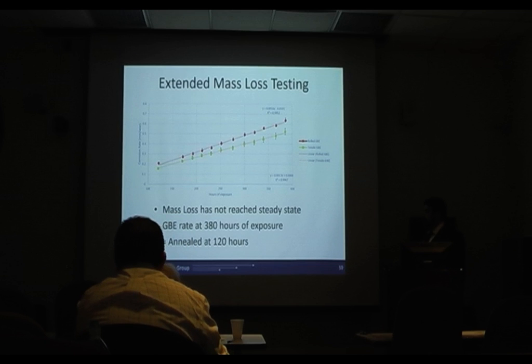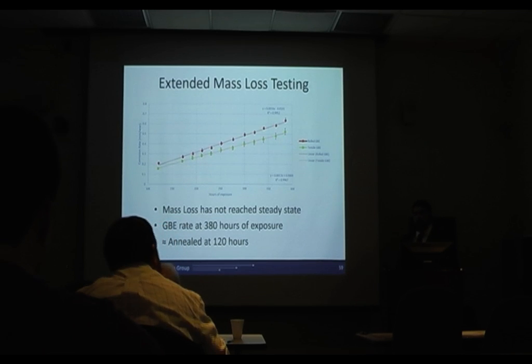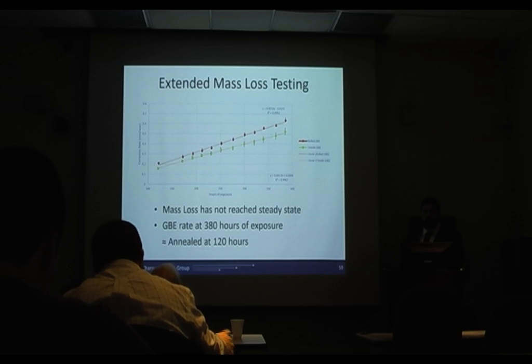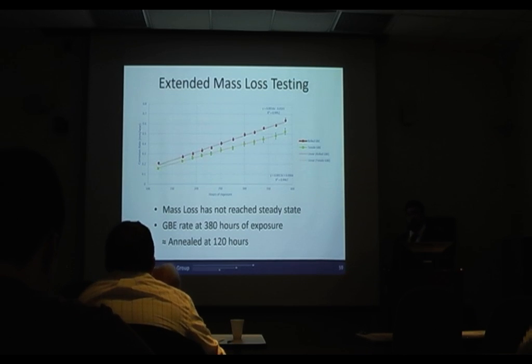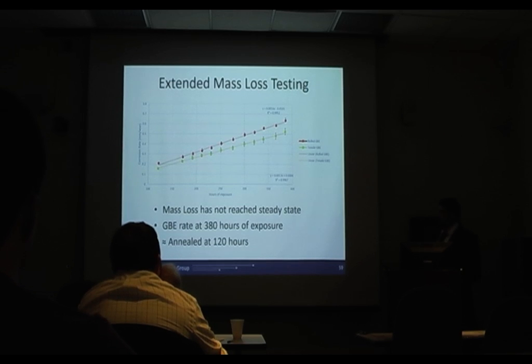And what we're seeing is that our rate, which takes time into account, is actually increasing as we go to longer exposures. This indicates that our grains are actually dropping out faster, and we're not getting to steady state. But if you think about this, it makes sense because we haven't actually dropped out our entire surface layer of grains yet. So it's not so much that it would be immune, it's just that it would be retarding the onset of grain dropout.